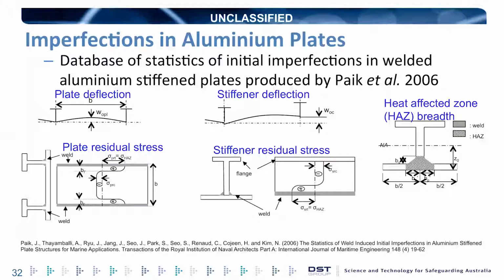Joe and Paik in Korea looked at aluminium ship structures and looked at the types of welding deflections that are likely to be seen in ship structures. And he identified these five types of deflection. First of all, the plate deflection caused by welding, stiffener deflection where the stiffener is shifted slightly, the breadth of the heat affected zone in aluminium structures, residual stress in the plate between welds, and residual stresses in I-beams on ship structures.